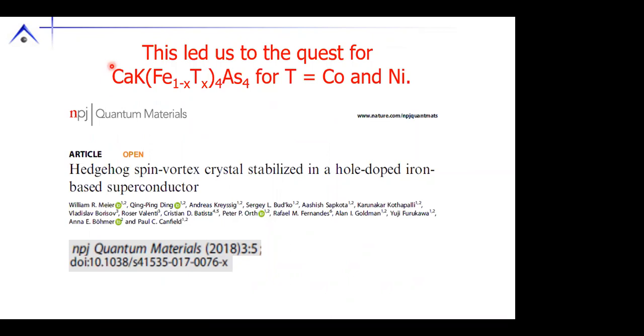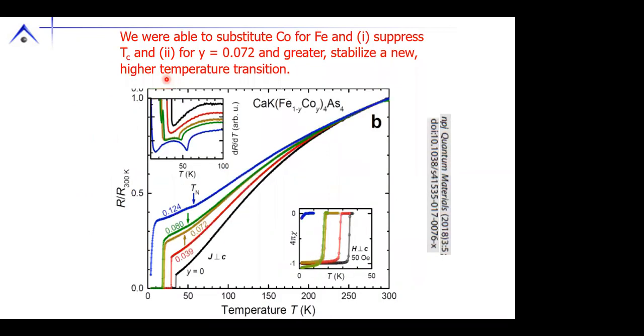So this led us to go from 4 to 5. We wanted to go to a quinary system where we were doing cobalt or nickel substitution on the iron side, okay? So we were able to do this for cobalt. As we add cobalt, we can see that we suppress superconductivity in the magnetization, we suppress superconductivity in the resistivity, and in the resistivity, we see a new feature kick in as we add more and more cobalt, seen clearly in the derivative, okay? We can do the same for nickel.